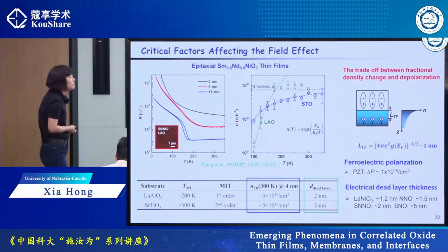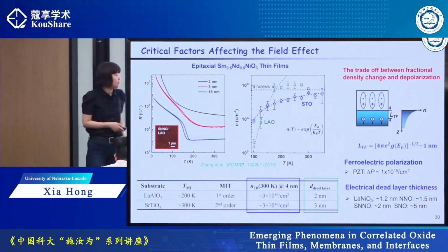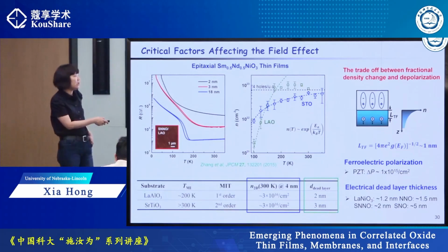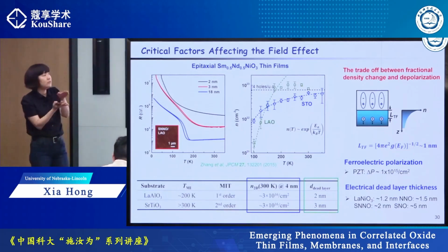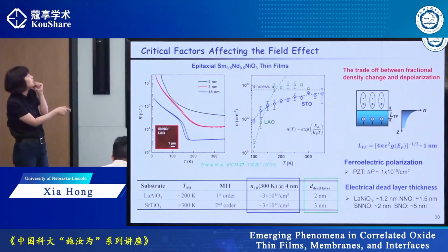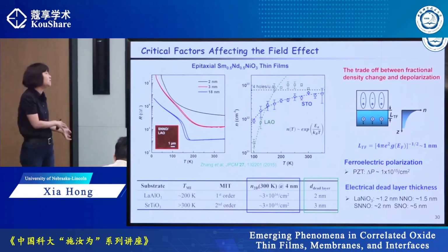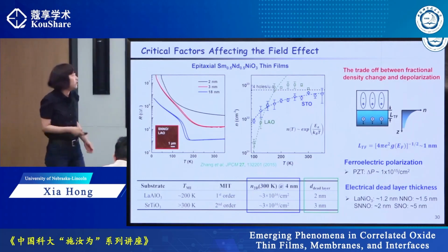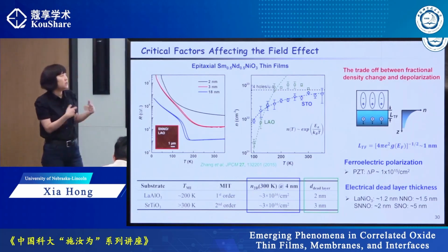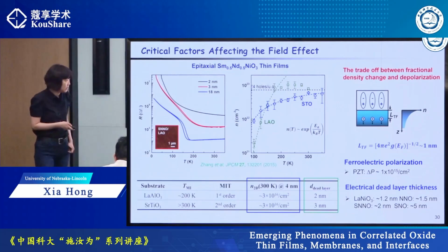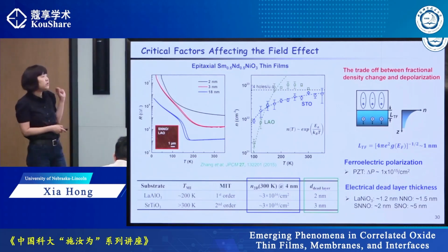The second important parameter is the dead layer, because apparently the 2D carrier density is always lower if I can work with a thinner film. But we discussed that if I reduce the film thickness, the film becomes totally insulating. Insulating film does not have free carriers. There's strong depolarization. I cannot really switch the polarization anymore. So we prefer to work with a material that has the smallest dead layer thickness.